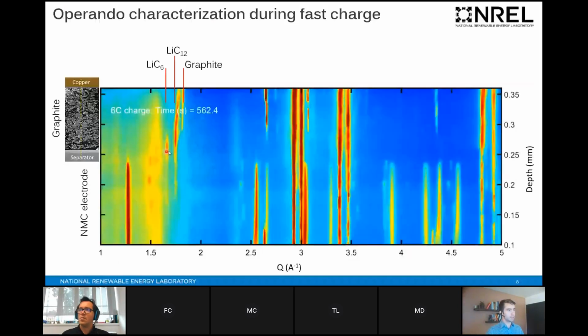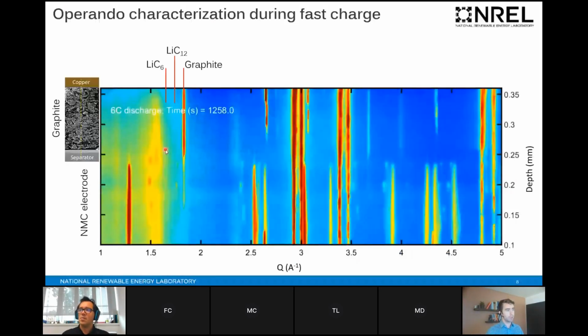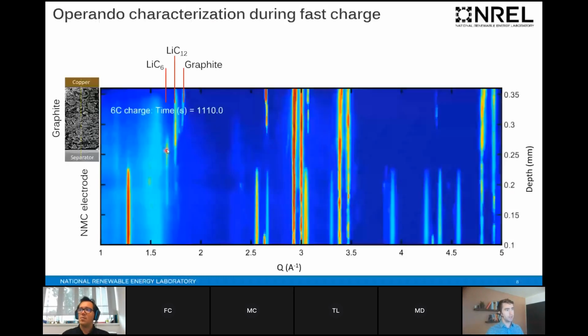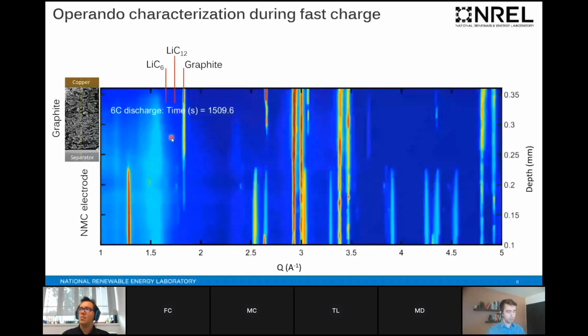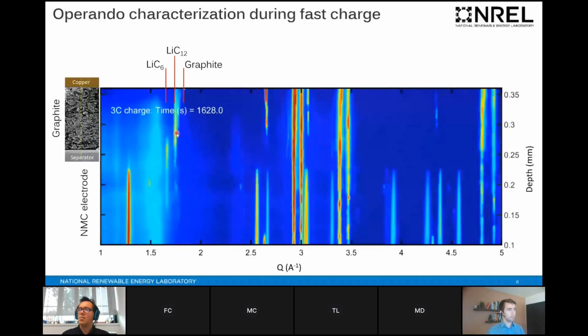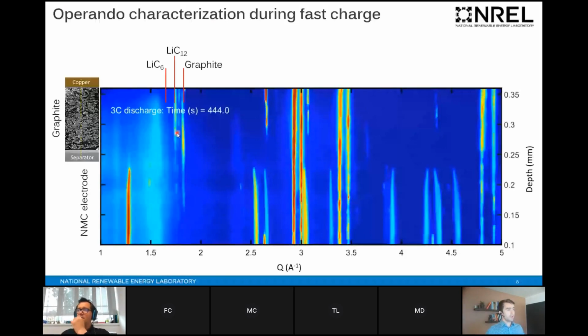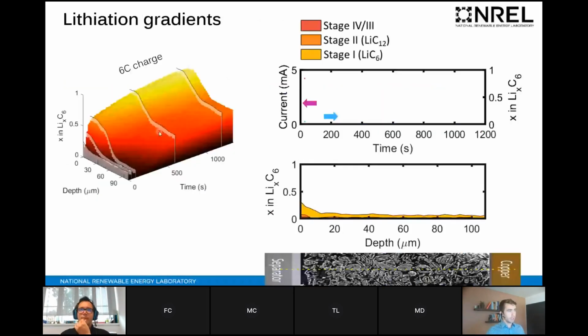And you can already see that at any point in time, often there's existence of 3 phases. So in some areas close to the separator you can see the LiC6 peak, LiC12, and graphite. So you can already see from the data that there are going to be very severe lithiation gradients in this cell. And when we conducted Rietveld refinement on this data, we were able to estimate the lithiation state, x in LixC6, as a function of depth and time.